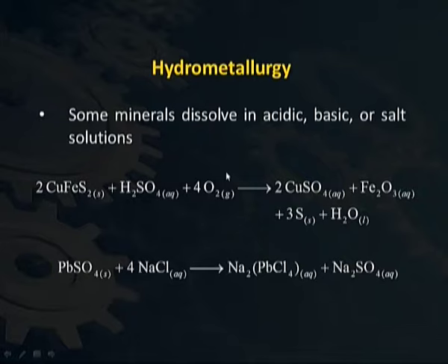Some minerals dissolve in acidic medium, others in basic, and others will require salt solution. Here is an example where we have used an acidic medium, and here again you can see that copper forms a sulfate, and the copper sulfate in solution form can be removed, and then the reverse reaction applied so that copper is precipitated out.